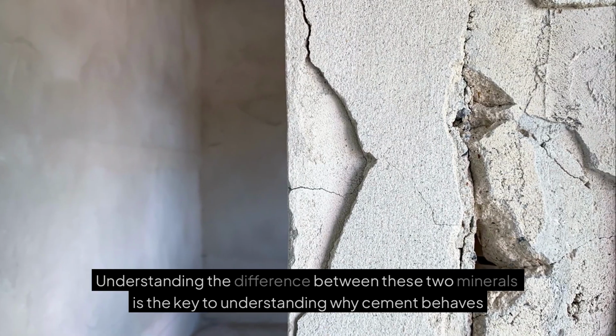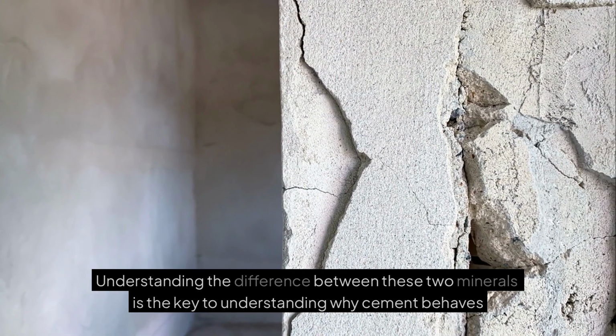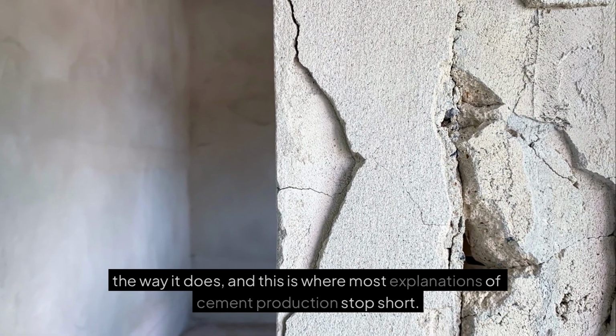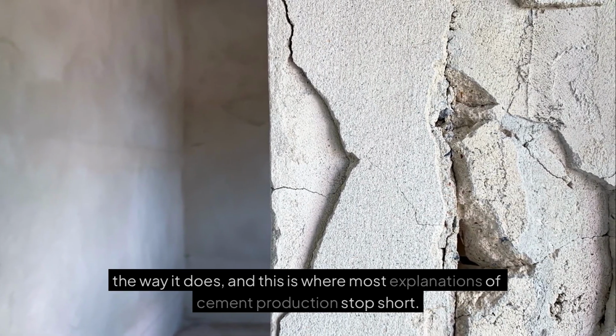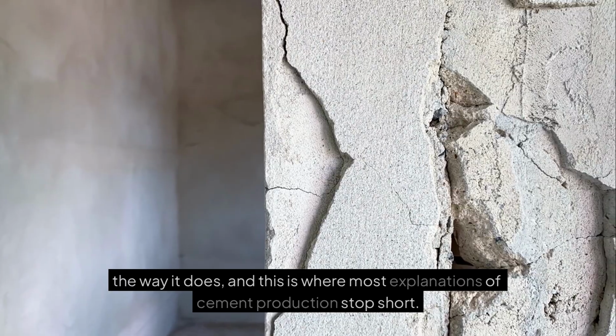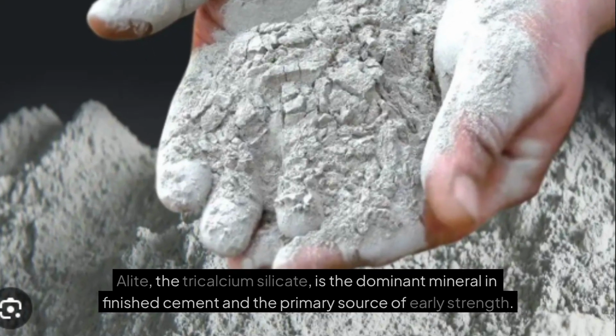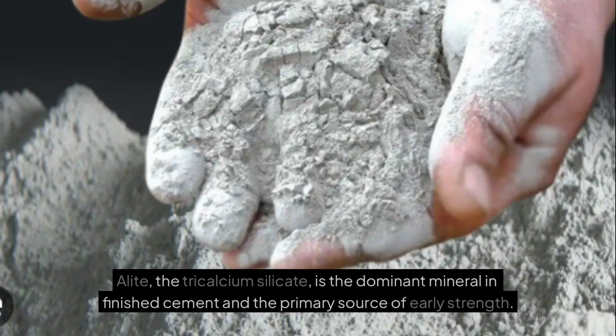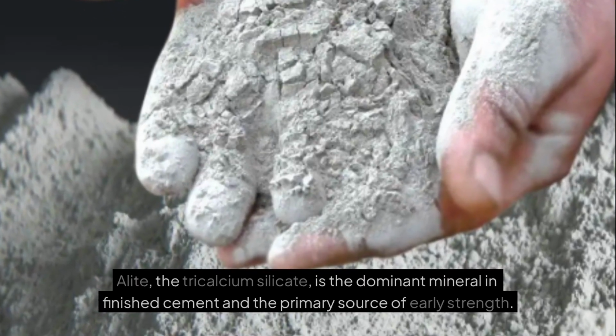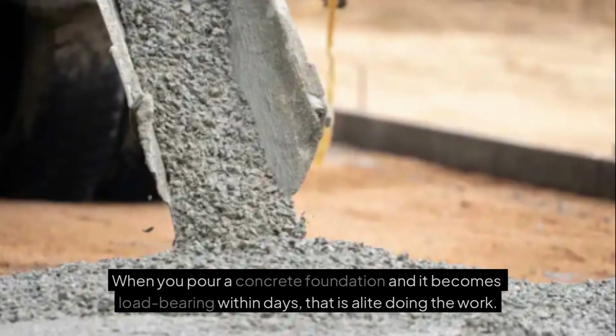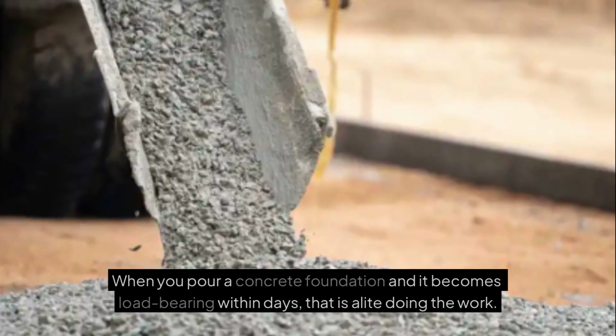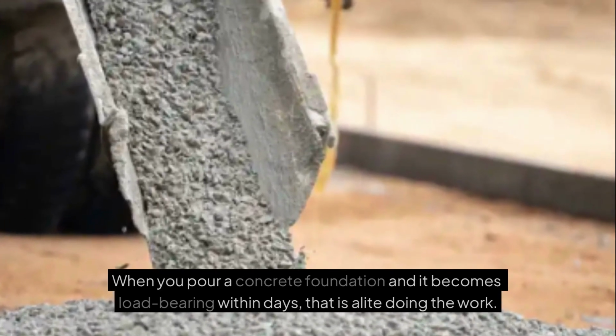Understanding the difference between these two minerals is the key to understanding why cement behaves the way it does, and this is where most explanations of cement production stop short. Alite, the tricalcium silicate, is the dominant mineral in finished cement and the primary source of early strength. When you pour a concrete foundation and it becomes load-bearing within days, that is alite doing the work.